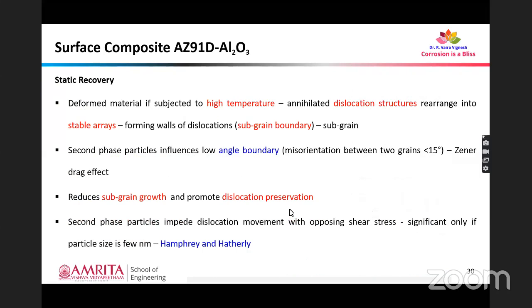And coming towards the microstructural evolution phenomenon that happens in FSP, it is through static and dynamic recovery and recrystallization that happen simultaneously in the material. Static recovery happens if the deformed material is subjected to high temperature. If so, there will be annihilation of dislocation structures into stable arrays, and these stable arrays form walls of dislocations. These walls of dislocations are called subgrain boundaries. These subgrain boundaries act as a hindrance towards dislocation motion, so they result in the formation of subgrains. So obviously they improve the hardness and strength of the material too.